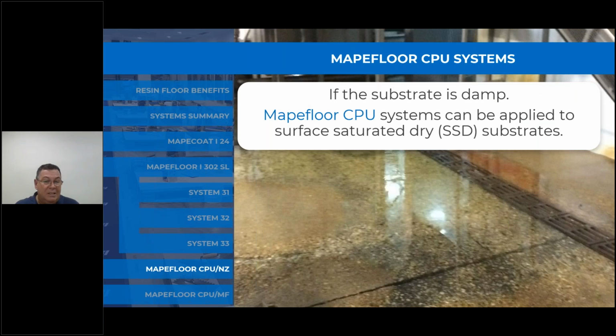Interestingly, if the substrate is damp, the Mapefloor CPU system can be applied to a surface saturated dry substrate. This is something that an epoxy resin cannot be applied to. You must wait until the substrate is down to a reasonable moisture content, generally speaking around 4%.